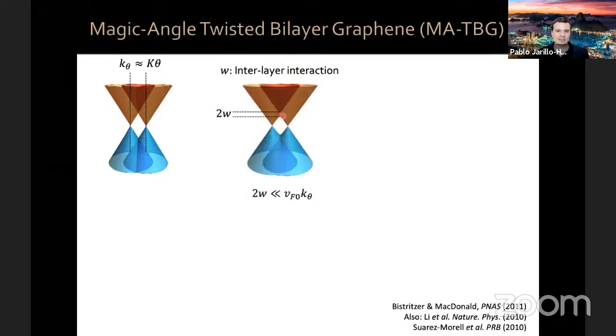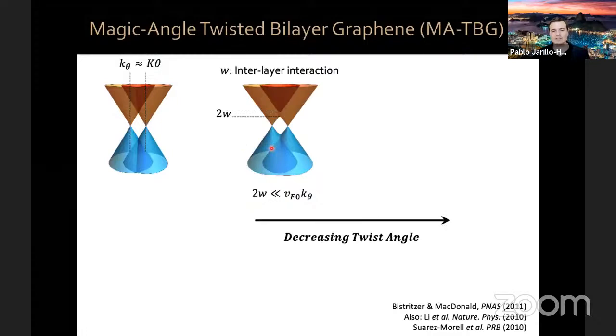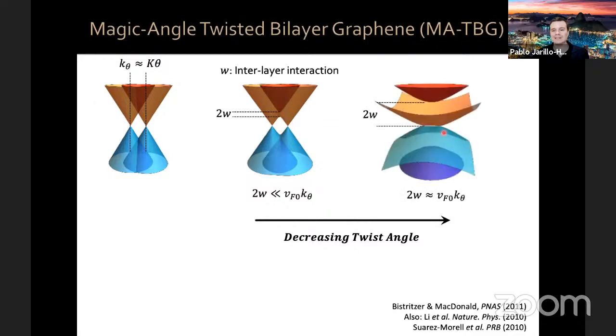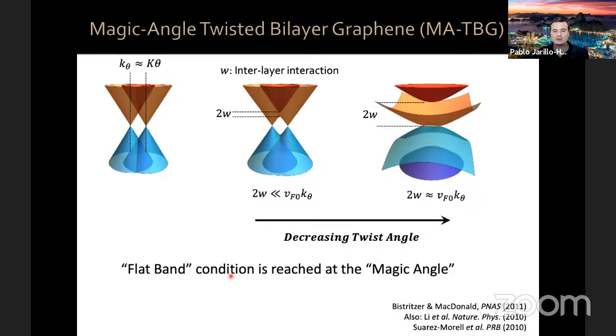This interlayer interaction or interlayer tunneling gives rise to bonding and anti-bonding states, similar to a hydrogen molecule, at this crossing point, leading to a band which gets pushed down towards lower energy. Now, this is the situation when 2W is much smaller than the energy of this crossing point, but as you decrease the twist angle, this band gets pushed down to lower and lower values until it gets pushed down all the way to zero energy. And that condition, which is known as the flat band condition, is reached at an angle which was coined by Bistritzer and MacDonald as the magic angle. So that angle is about 1.1 degrees for graphene on top of graphene.